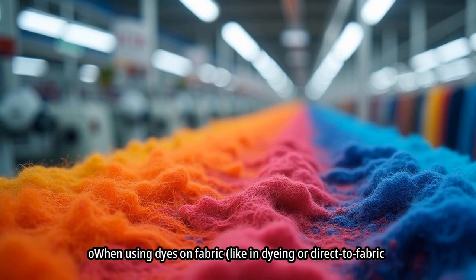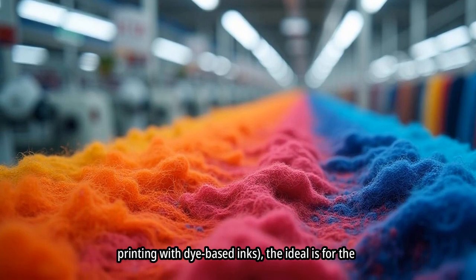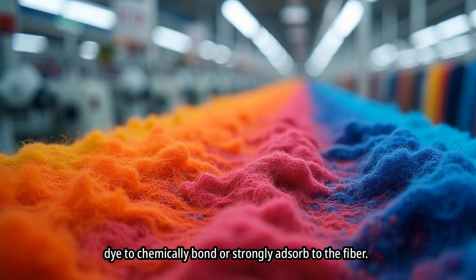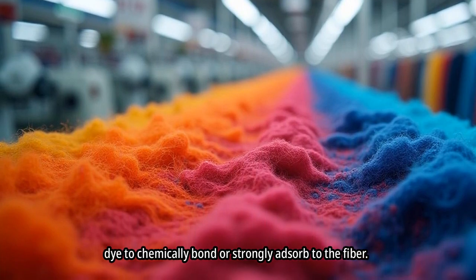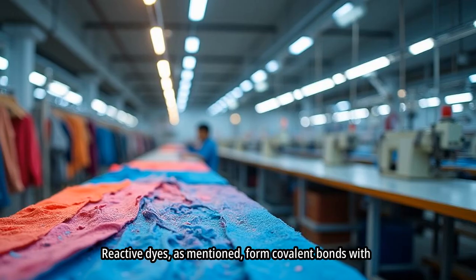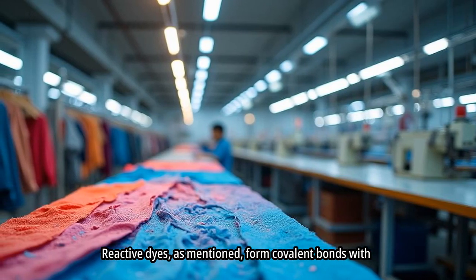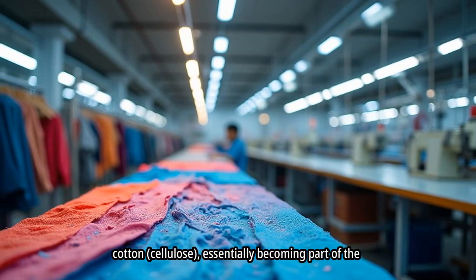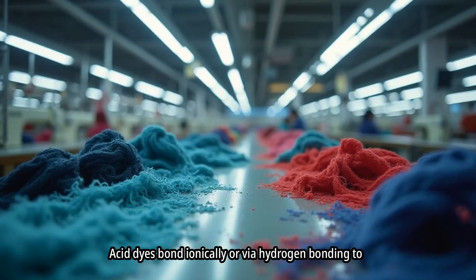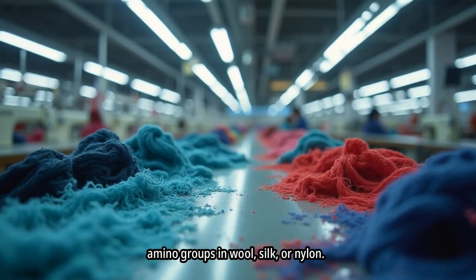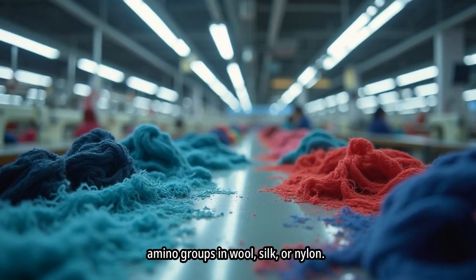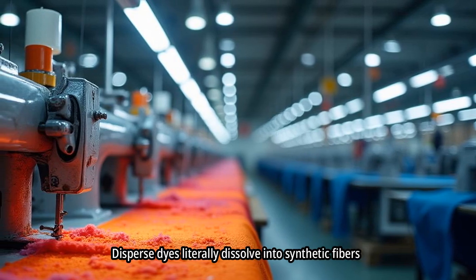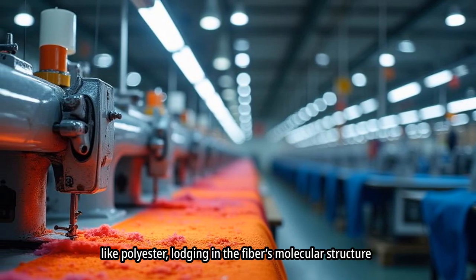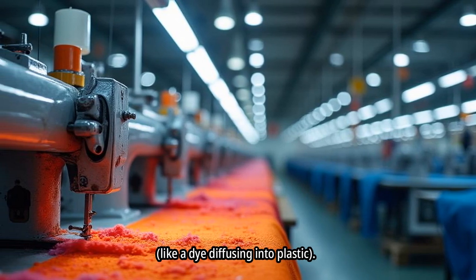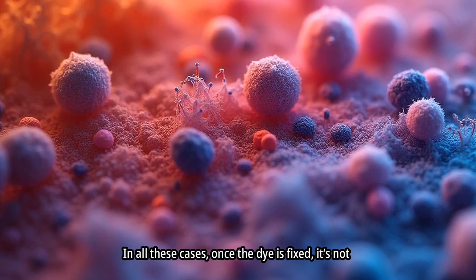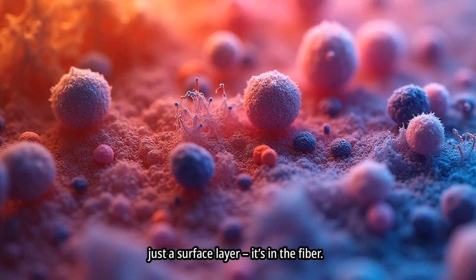When using dyes on fabric, like in dyeing or direct-to-fabric printing with dye-based inks, the ideal is for the dye to chemically bond or strongly adsorb to the fiber. Reactive dyes, as mentioned, form covalent bonds with cotton, cellulose, essentially becoming part of the fiber. Acid dyes bond ionically or via hydrogen bonding to amino groups in wool, silk, or nylon. Disperse dyes literally dissolve into synthetic fibers like polyester, lodging in the fiber's molecular structure, like a dye diffusing into plastic. In all these cases, once the dye is fixed, it's not just a surface layer. It's in the fiber.